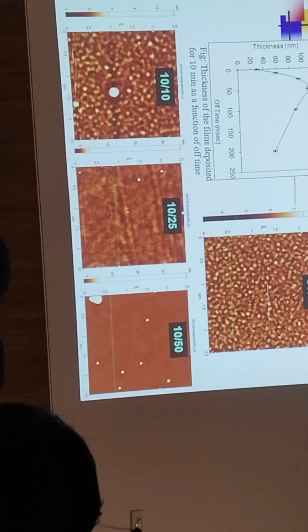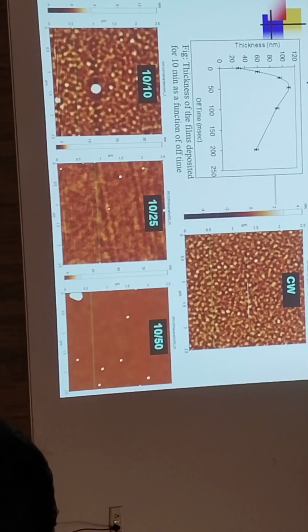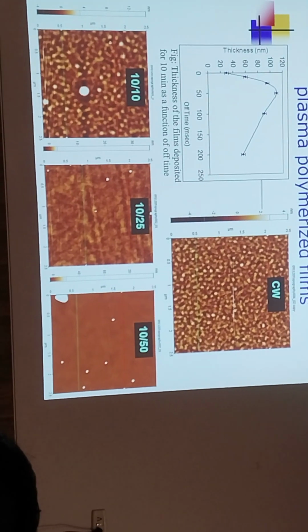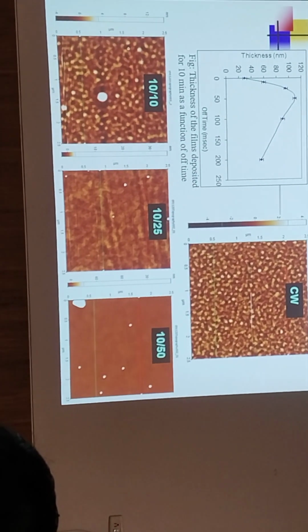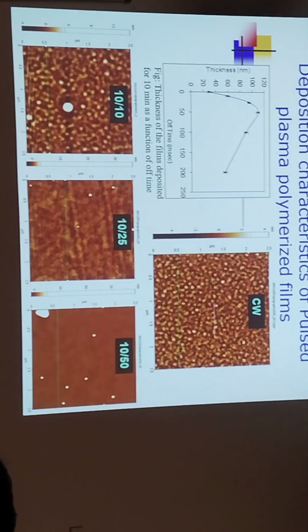Whereas as we increase off period, 25 millisecond off and then next is 50 millisecond off, the 10 millisecond on period is kept constant. So as we increase off period, whatever the species, they get sufficient time to settle, even the lateral movement on the substrate also, and because of that the surface is now quite smooth. So not only the surface chemistry but also surface morphology can be tailored precisely with the help of pulsing nature of plasma, which is not possible with continuous wave plasma.